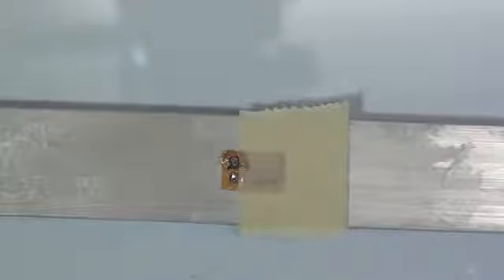If you pull the solder away first and then keep tapping it with the soldering pencil without the flux present, the surface tension is going to reappear and it's going to drag the solder with it. So that's the trick. Another thing that I'll mention here while VJ is preparing the wire is the soldering that he's doing is at a very low temperature.